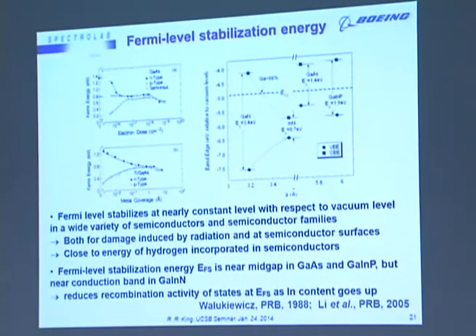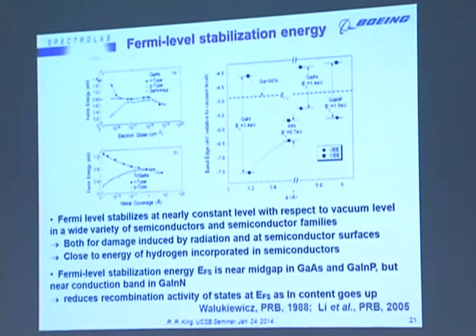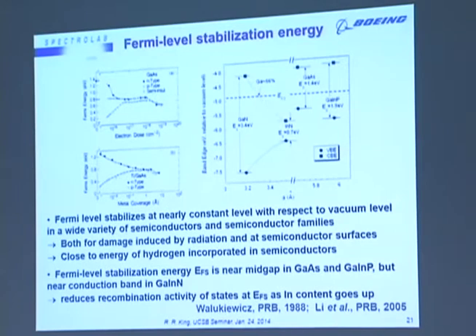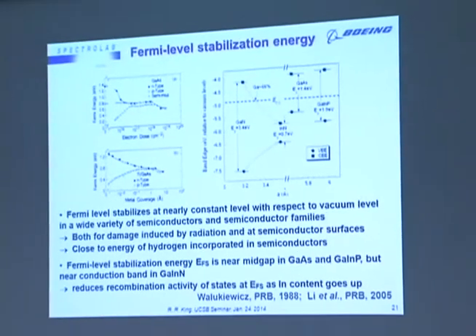So there's also this concept of the Fermi level stabilization energy, where damage to the lattice forms defects at about the same energy with respect to the vacuum level. For instance, in this case, as one changes composition from gallium nitride to indium nitride in the gallium nitride system, which many of you are extremely familiar with, that Fermi level stabilization energy goes from being a state that's in the gap to a state that's in the conduction band, and as a result becomes far less active in terms of its recombination activity as one increases indium composition.